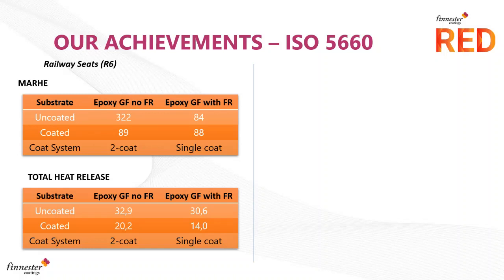So we can take an uncoated epoxy glass fiber composite without any fire retardant additives or technology, and that will give us a number of 322. So rather high number for MARHE, well beyond the hazard level requirements. But if we coat that, in this case with a two-coat system, we can bring that just below the threshold of 90 into a hazard level 2 application. So we can make a dramatic difference in the performance of this parameter by putting the two-coat system on this substrate.